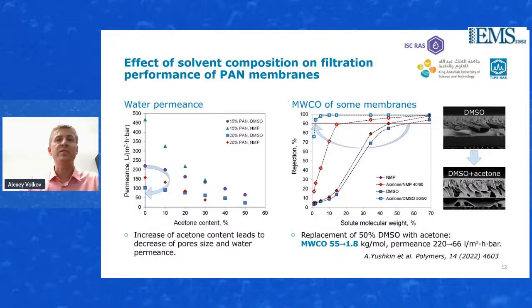for PAN material. Of course, that is with a trade-off, so we are also losing the permeance. But the most important thing is that by selecting the proper composition of the casting solution, we can also change the molecular weight cutoff of the resulting membrane. And on the right-hand side, there are the same pictures of the DMSO membrane, when we use only DMSO, and the bottom one when we mix DMSO with acetone, and that actually impacts the porous structure.